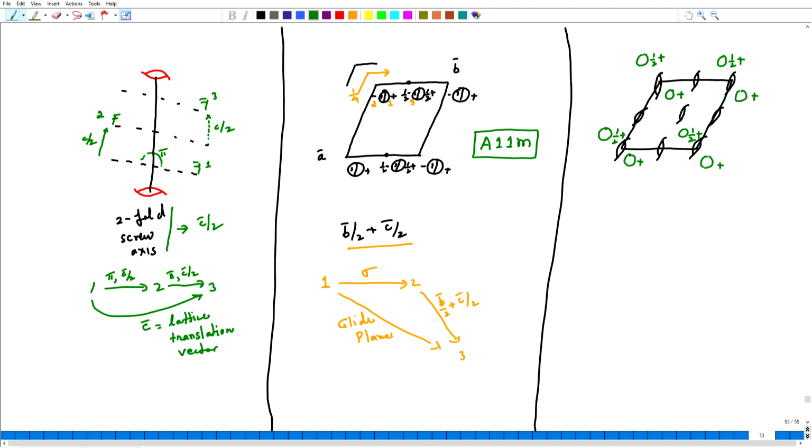Now, what should I call this space group? Well, it can be called as primitive to start with, then 1 and 1 along A and B. But now, along the C, the unique axis, there is a two-fold rotational symmetry. So, I will need a symbol for that as well. Well, the symbol for that would be, so if I come back here, what symbol should I put? The symbol 2 sub 1 is put. Now, I will explain the logic of this symbol when we discuss the screw axis in more detail in the next lecture.